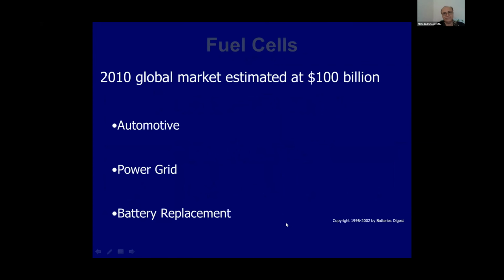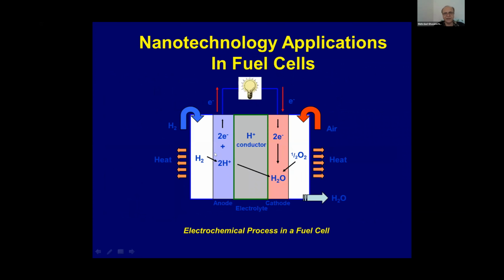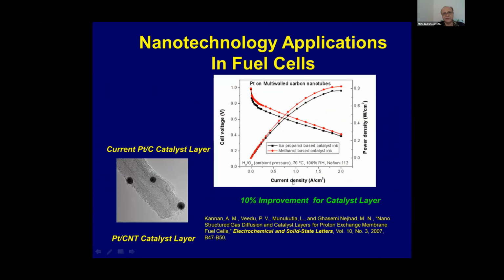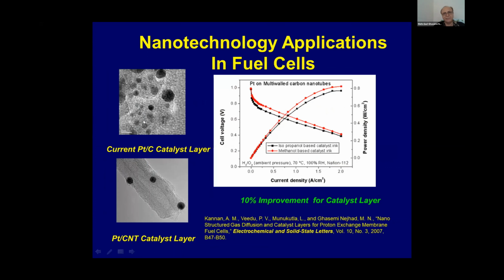Also, there is an application to the fuel cell. In a fuel cell, you have Nafion, the proton exchange membrane, here. Then you have a catalyst layer, this green, and then these two parts are the gas diffusion layers. So we showed that we can improve the performance of the catalyst layer by using nanotechnology. We put platinum nanoparticles on a bed of carbon nanotubes. Other researchers had 40% saving in nanoparticles, but performance was the same as without. So we had 60% saving in platinum, and we have 10% improvement.